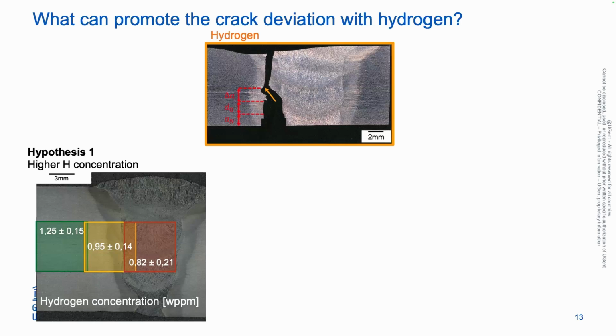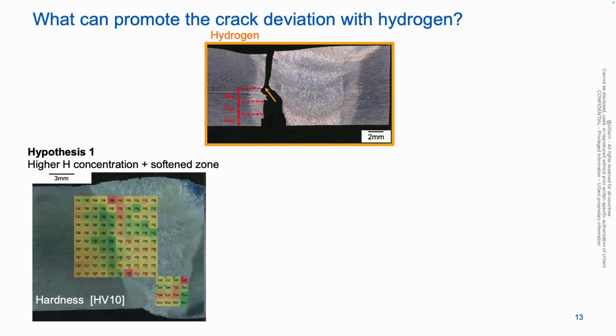This is not the only thing. It's in combination with a softened zone that we see at the border of the heat-affected zone and the base material. This can maybe explain that we can have more dislocation mobility in that area, which in combination with a slightly higher hydrogen concentration can enhance the effect of hydrogen in that region.